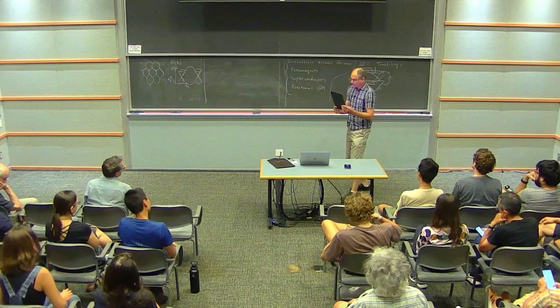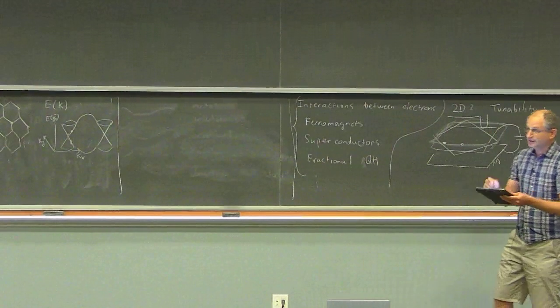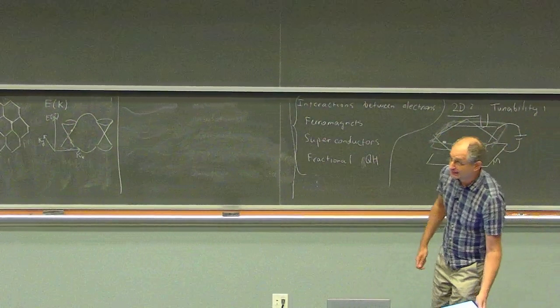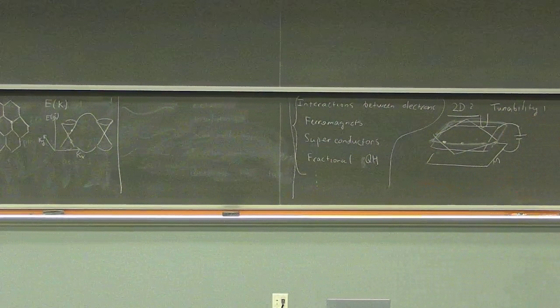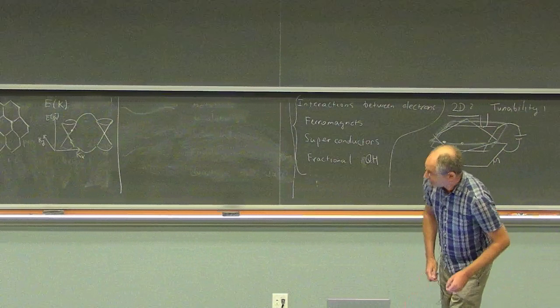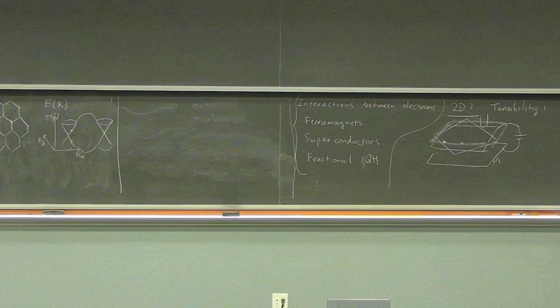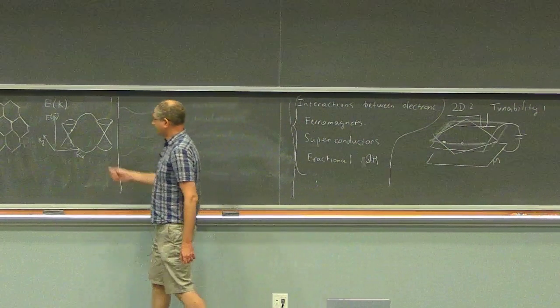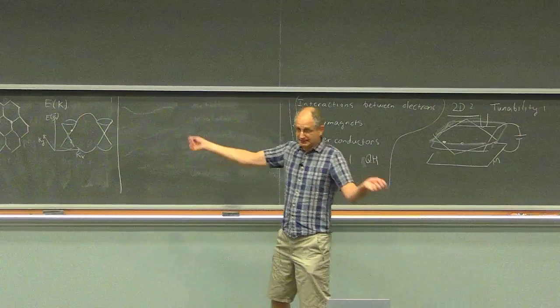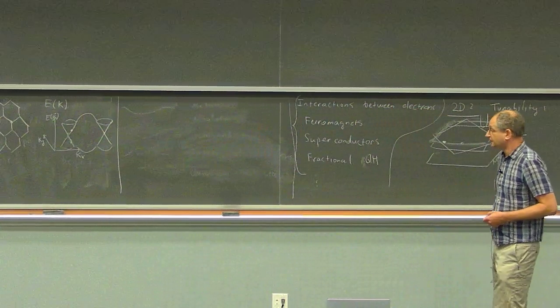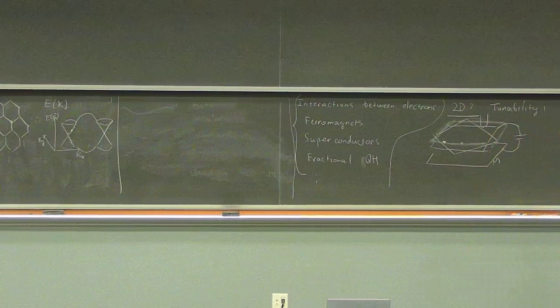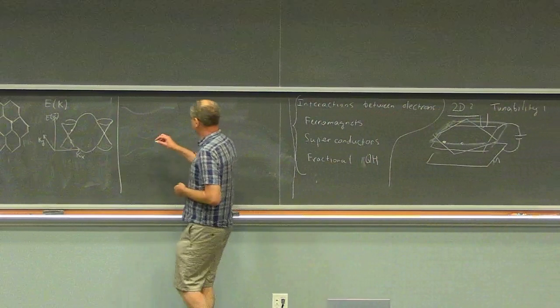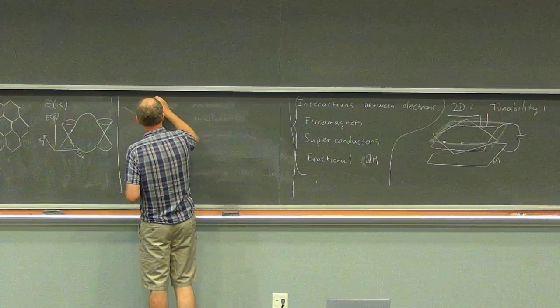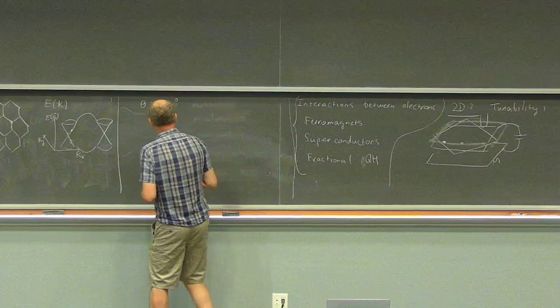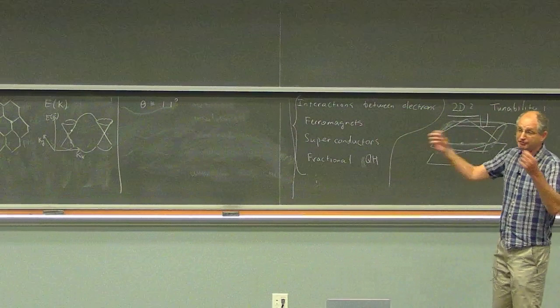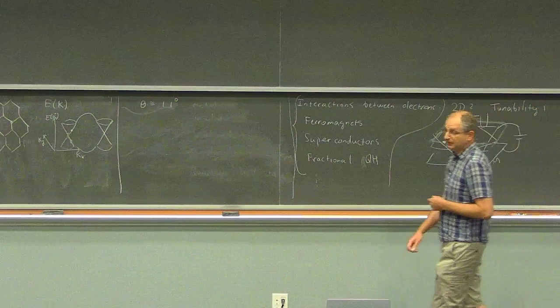So what are the electronic properties of electrons that are moving on the background of this kind of artificial lattice formed by the Moiré pattern? We get a whole new material, and this is where the magic comes. You really have to solve the quantum mechanical problem of electrons moving in this large-scale lattice. This lattice can be 100 times longer than the distance between carbon atoms, and the prediction, about 12 years ago, was that there's going to be some special value of this angle, a twist angle of about 1.1 degrees, where the dispersion, modified by this artificial lattice, is going to be radically different.